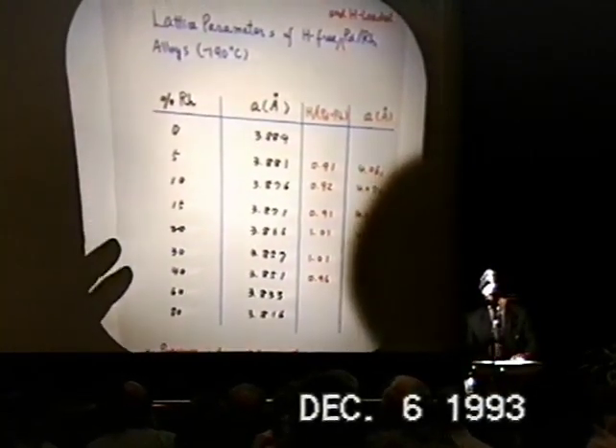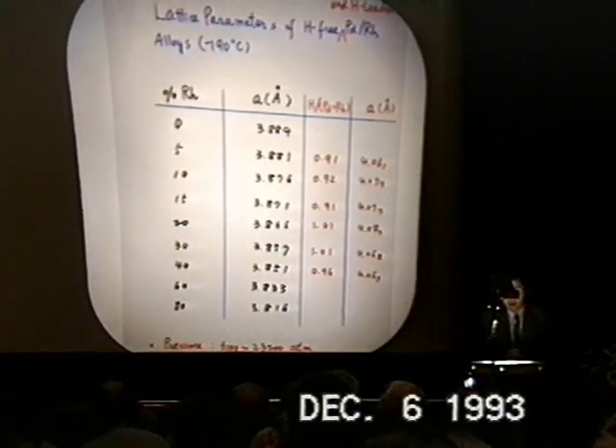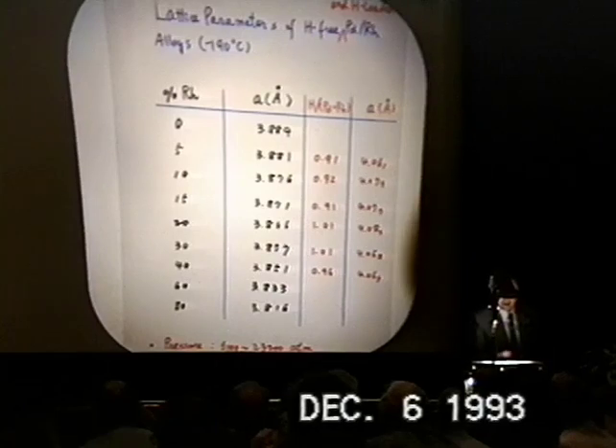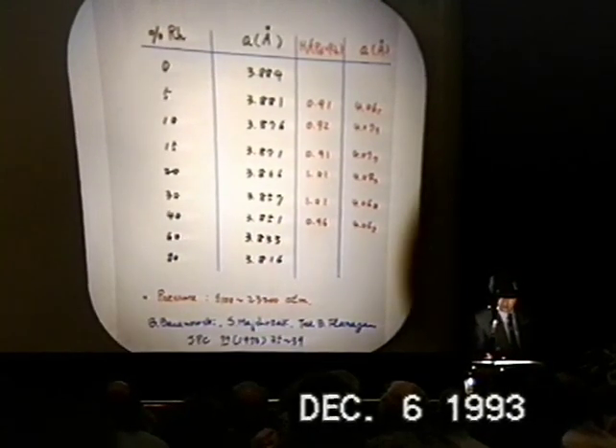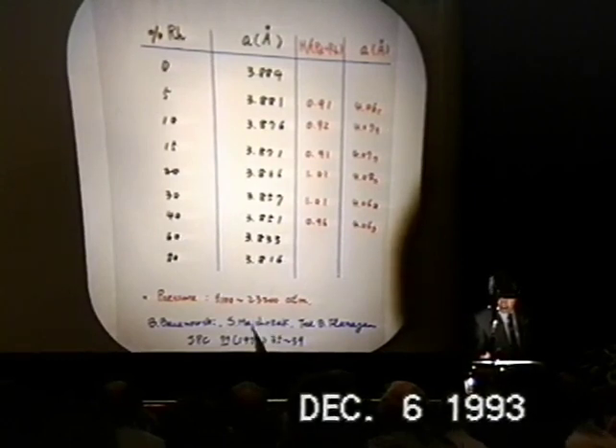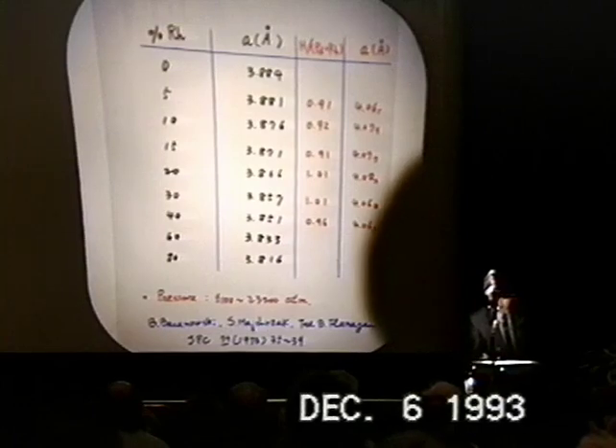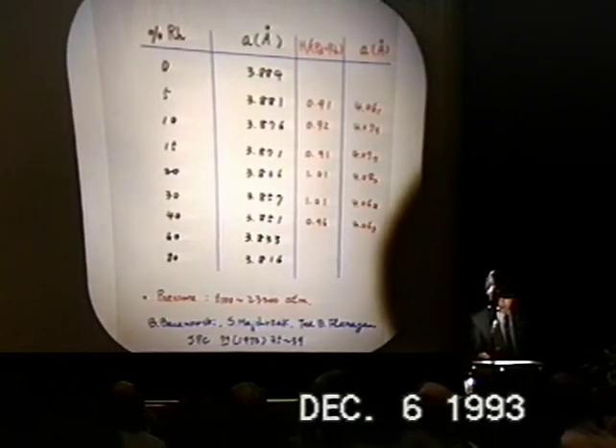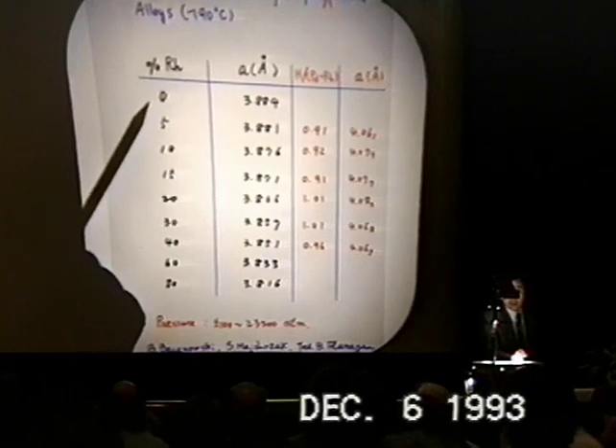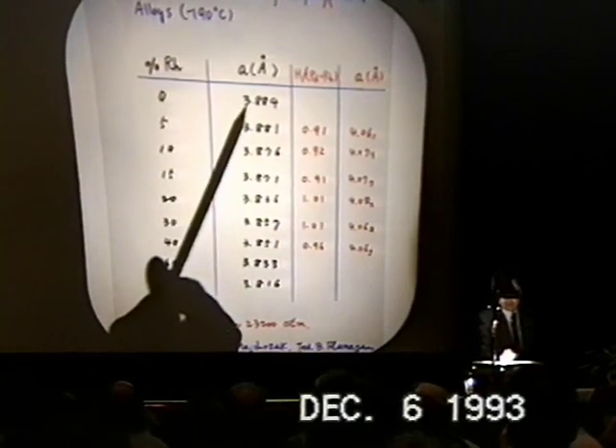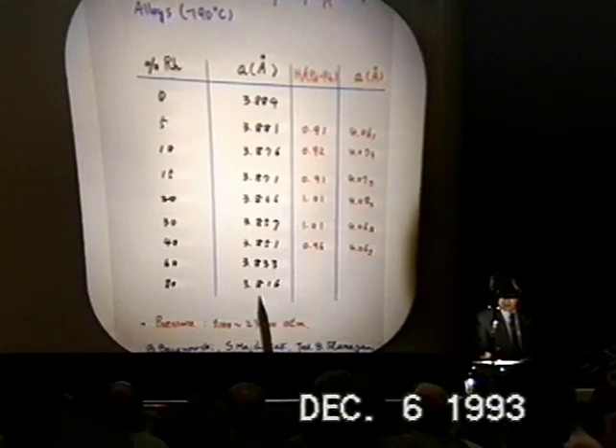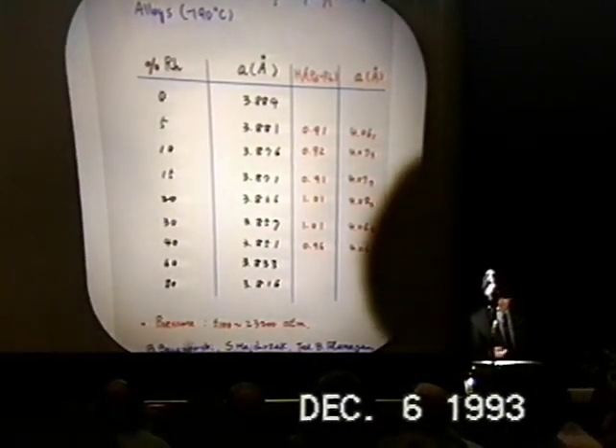So after this, we decided to go to new materials, which is palladium rhodium. And I'm showing you by this figure that it is known by the work by Baranowski, I can't read this, and also by Flanagan and first in Journal of Physical Chemistry in 1973, that when we increase the content of rhodium in the palladium rhodium alloys, we decrease the lattice parameter of the alloy from 3.884 to something like 3.816 at 80% rhodium palladium alloys.